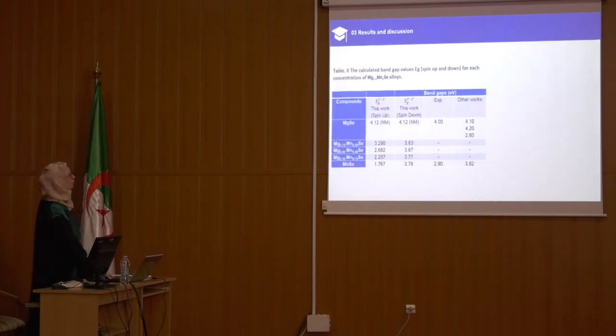In this table, we present the calculated band gap values for each concentration. The value of the binary MgSe is equal to 4, which is in good agreement with other theoretical and experimental works, and this is due to the use of the mBJ approximation.